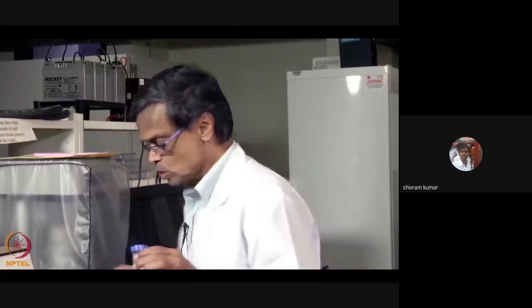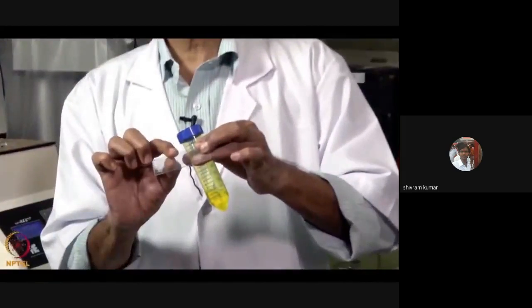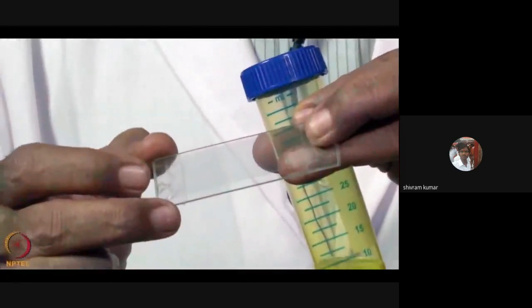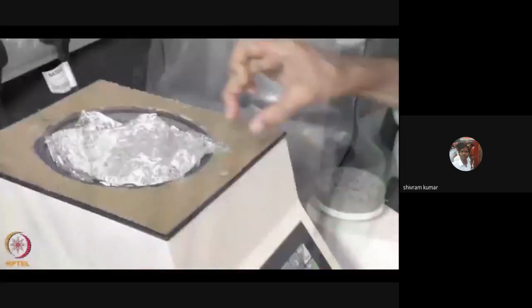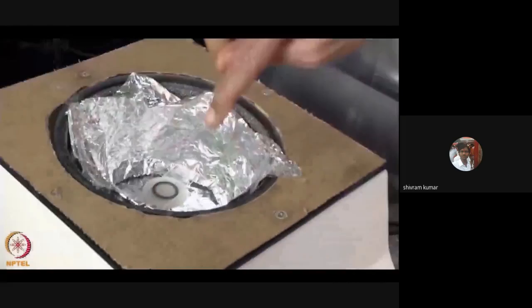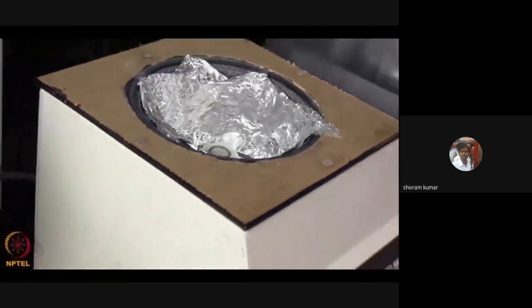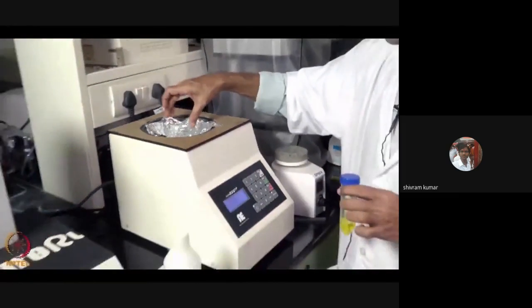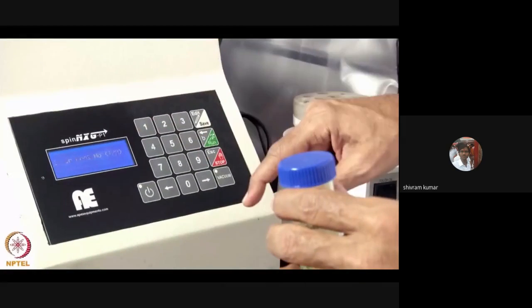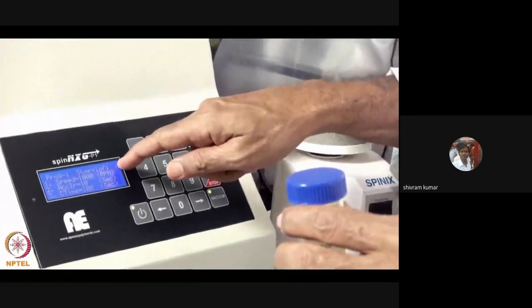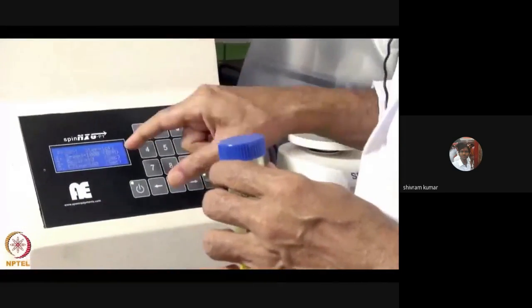As I said before, polyester is widely used for large diameter vascular grafts, diaphragm valves and so on. So polyester is fixed to glass slide using a tape, and it is placed inside the spin coater here. This spin coater also has a vacuum arrangement so that the solvent that's coming out will be sucked out. Now we load the program. As you can see, it will be rotating at 1000 RPM, acceleration in 10 seconds, and then contact time is 100 seconds. We press 1 here and then we say run.